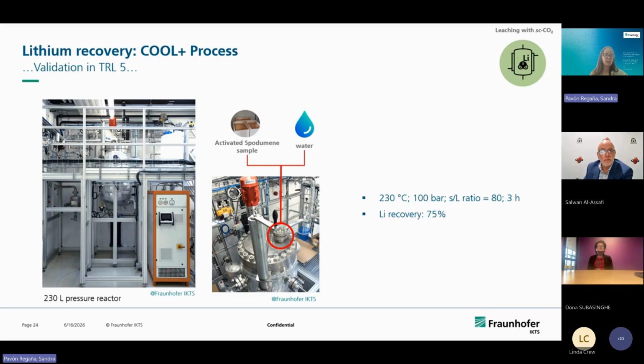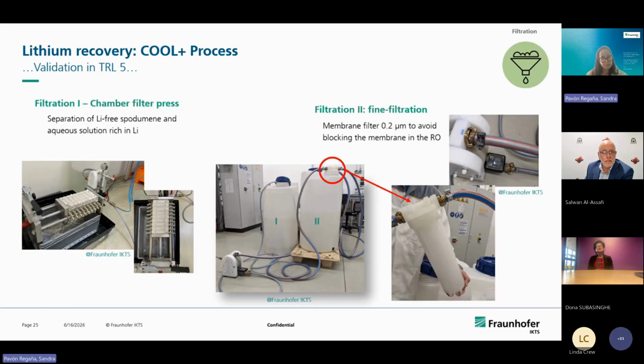This is our pilot plant in Freiberg, in our Fraunhofer facilities, a 230 liter pressure reactor. And then we are adding this activated spodumene sample together with water. We are increasing the temperature and the pressure using a solid-liquid ratio of 80 for 3 hours, and then we are able to recover 75% of lithium. That is why I said before that we are in the last phase of optimization. We are trying to increase this percentage in the pilot plant to 80-85, in order to meet the threshold requirement from the battery regulation, which claims that we must recover 80% of lithium. So we are on the way.